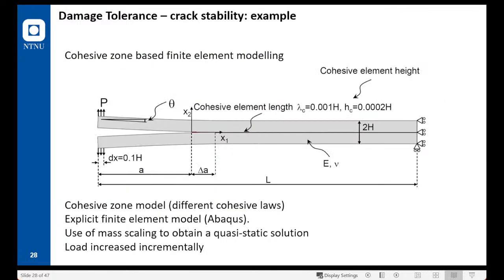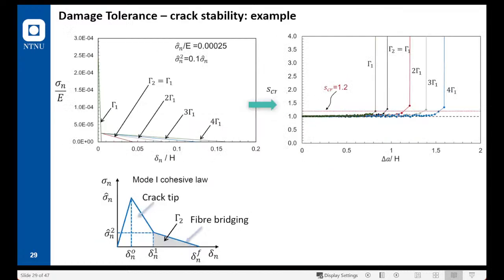We have done some parametric studies with finite element calculations where we have embedded a cohesive zone here and applied forces to grow the crack for different cohesive laws, where we have varied the cohesive law corresponding to the large fracture process zone. We have kept the same fracture parameters for the crack tip. These are the actual cohesive laws, and we can see that as we increase the energy dissipated in the bridging zone, the crack is stable for a larger period. This is the crack length, and this is the stability criterion. So we see how the material properties will affect the stability of a structure.